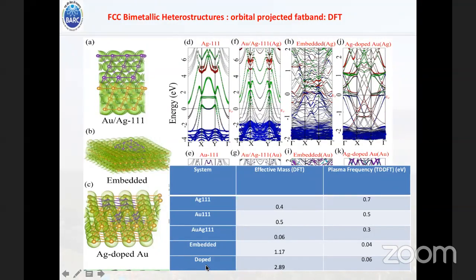And for the embedded and doped systems, there is some indication of carrier localization, and you can see here that in comparison to Au and Ag111 surfaces, for the embedded and doped system there is an increase of effective mass. So there is one order of magnitude increase. And don't look at this plasma frequency stuff. I'm explaining it afterwards. And so next we have calculated the Fermi surfaces for all those three systems, and there